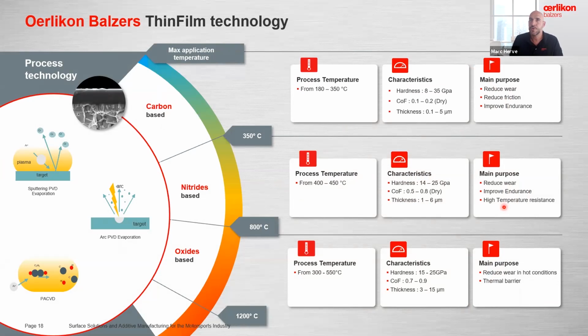If you look for temperature protection, for example on an exhaust valve, we might go to a different kind of coating that resists much higher temperature. And if we want to go even higher, then we might have to move to oxide coatings that can resist more than 1000 degrees C. So the coating industry is quite complex, and depending on the part, depending on the application, we will have to pick different technologies.